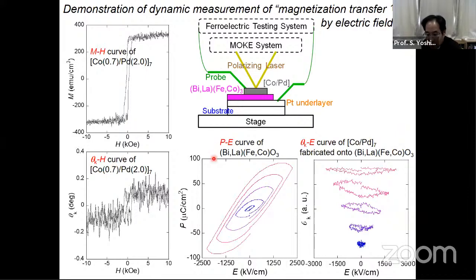And this is the result. The film structure is similar to the previous one. Multiferroic materials here and metallic magnetic materials here. And this one is the PE curve of this material. And this one is the Kerr loop of this metallic magnetic material. And this data is the magnetic Kerr effect of this material against the electric field here. So you can see the hysteresis here.